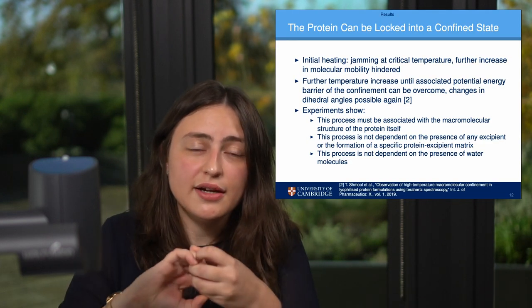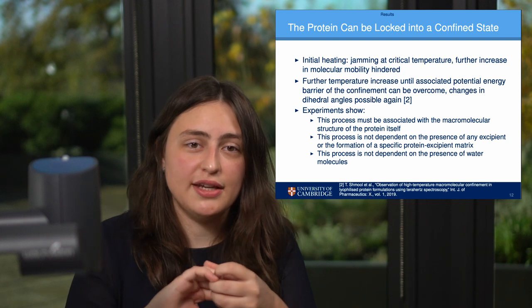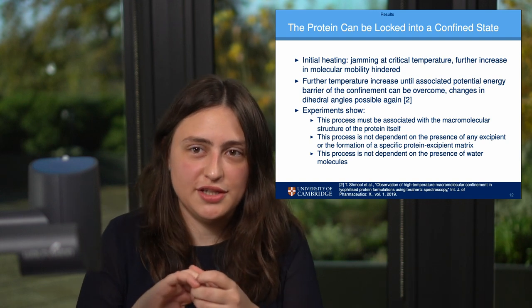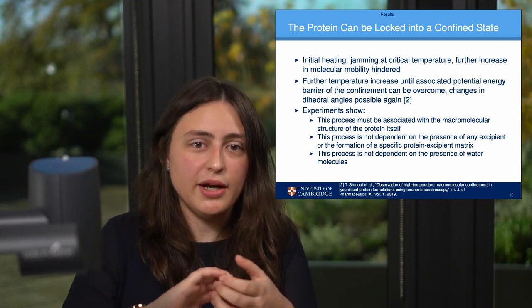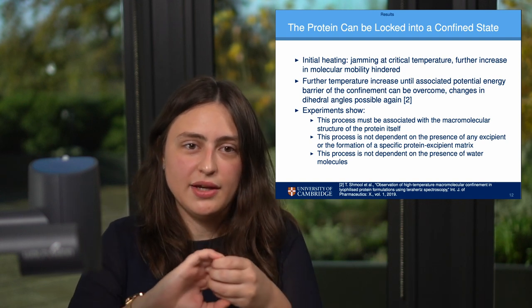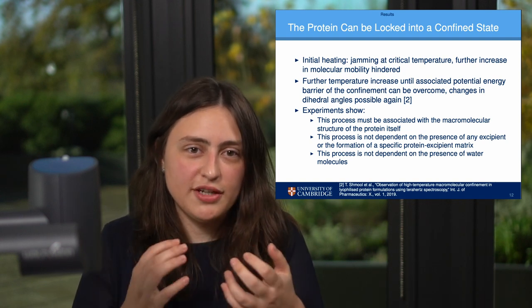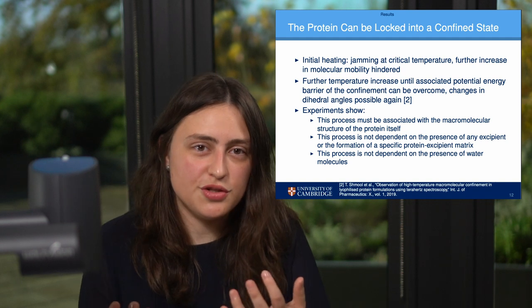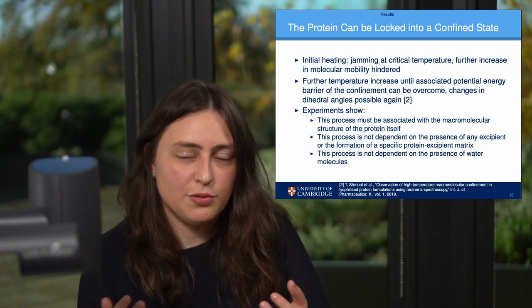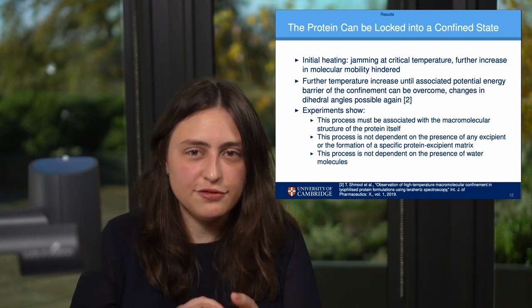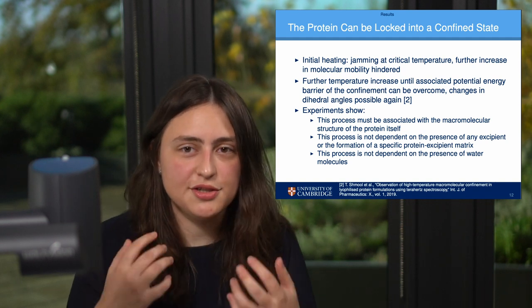The molecular mobility cannot increase further, even as we increase the temperature. Only if we increase it quite a bit can we jump out of that well into another well, which means other dihedral angles, other motions, and other conformations become possible.